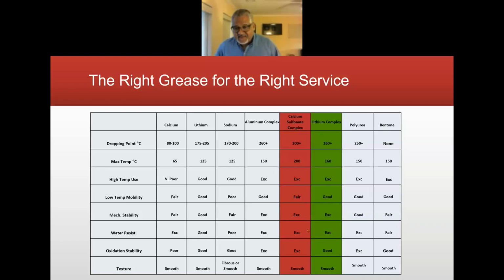Water resistance, both excellent. They'll both absorb water, but as far as staying stable in water, calcium sulfonate grease stays stable in water. Matter of fact, I had a novice friend of mine rub calcium sulfonate grease emulsified with water, and one without water emulsified, and asked which one's a better grease. And she chose the emulsification of calcium sulfonate in water. So it functions well in water, still gets wear protection, still stays in place, still gets good corrosion protection in the presence of water. Unlike lithium complexes and aluminum complexes, you really have to fortify aluminum complex and lithium complex to perform as well as the natural protection against corrosion of a calcium sulfonate complex grease.